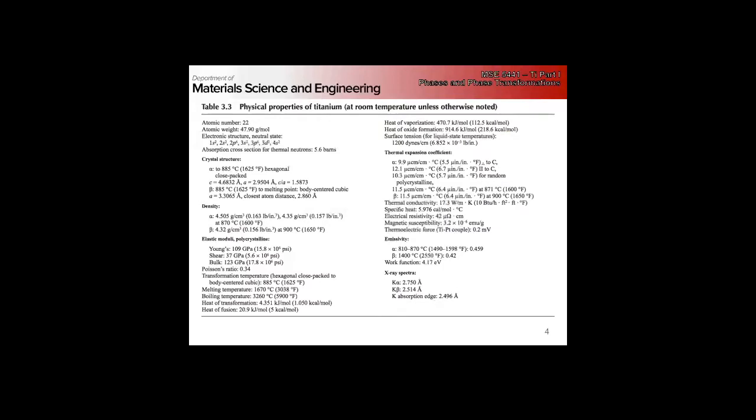What are the other major industries that see a lot of titanium use? Biomedical, because it's biocompatible. All right. There's another big one. Right. It's a property that is not so easy up here. Right. So if I told you titanium has a very good passivating oxide layer, right? What would that imply to you guys? Good corrosion resistance, right? So places where you have hot corrosion issues, right? Chemical, petroleum, right, are also going to be key places.